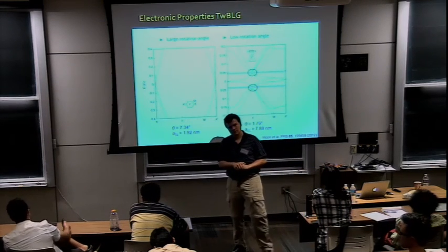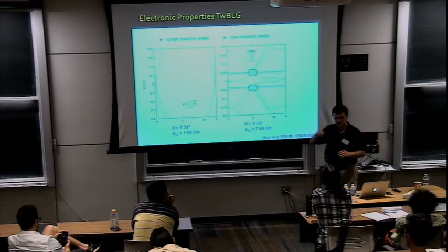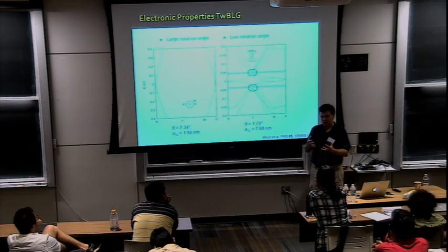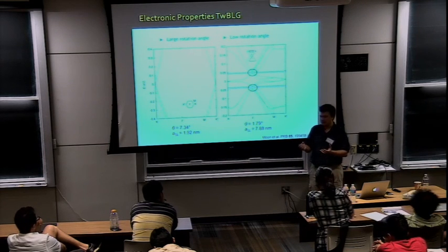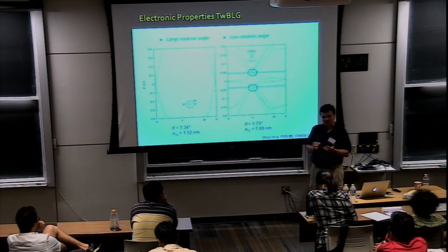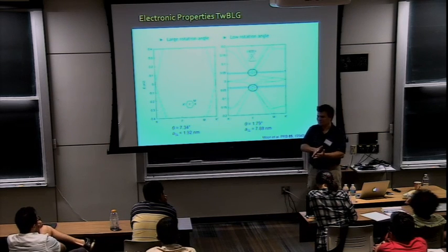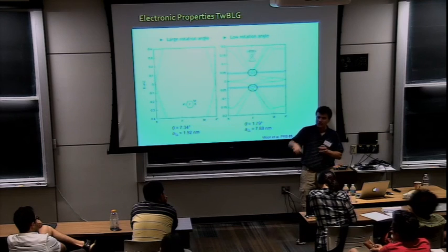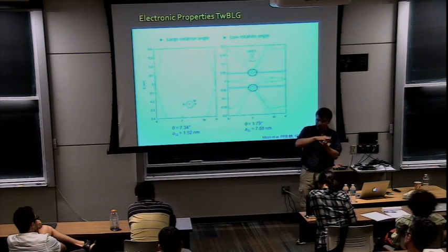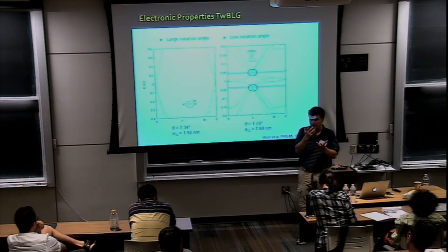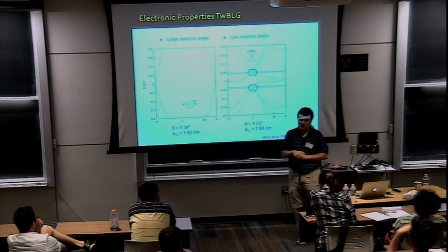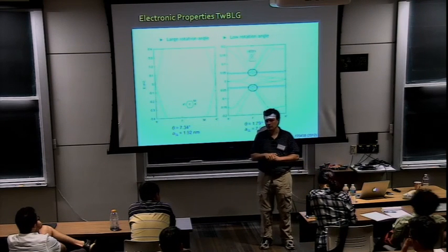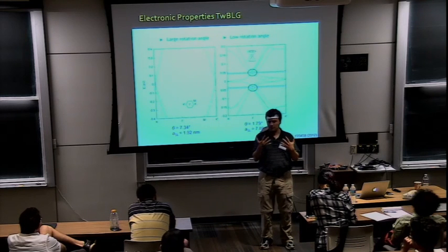As a follow-up question, are you aware of other systems that people have realized with the Hofstadter butterfly? I included a couple of references to systems where people had a 2D electron gas and lithographically defined gates to create a periodic structure. The problem is that no matter how good your lithography is, it turns out that it's worse than atomic lattices stacking on top of each other. Because the length scales were larger, the energy scales associated with the features were smaller, which means that at the temperatures and levels of disorder they had available, the features were not as pronounced as in what we have. There was evidence of it, some strong indications that people had seen the Hofstadter butterfly, but it was not as pronounced as in these papers.